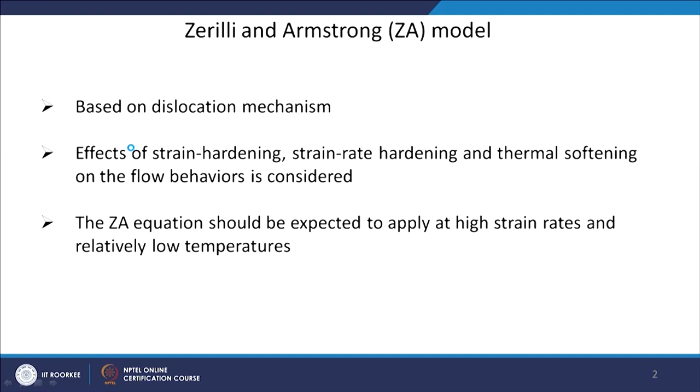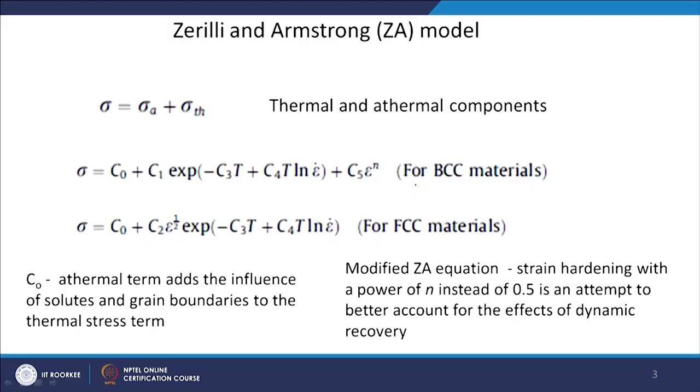This particular equation can be applied for high strain rate and relatively low temperature conditions. The stress is calculated by considering two contributions: one is a thermal contribution and another is an athermal contribution which does not depend on temperature. By combining these two different effects on the stress, you are able to find out the flow stress of the material.